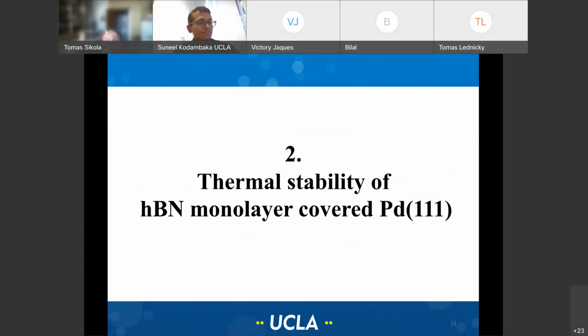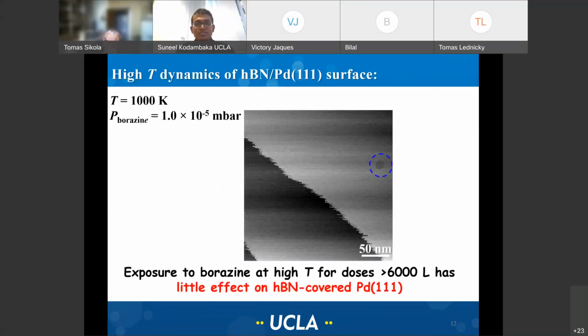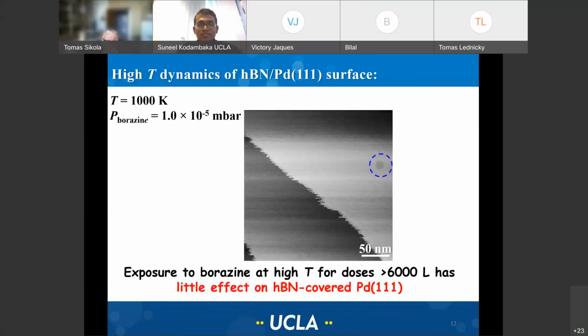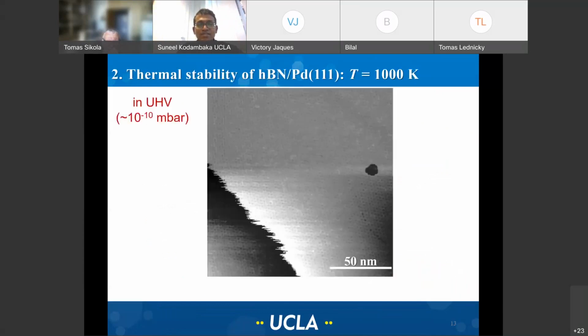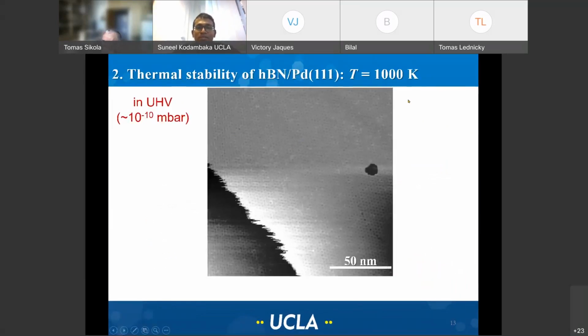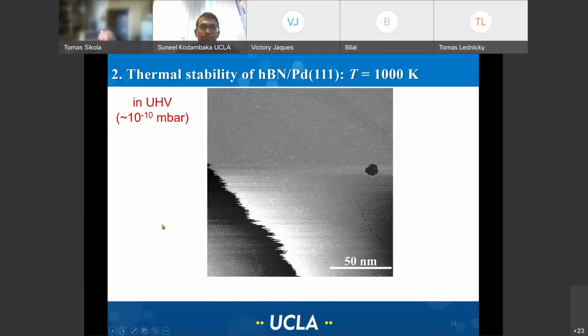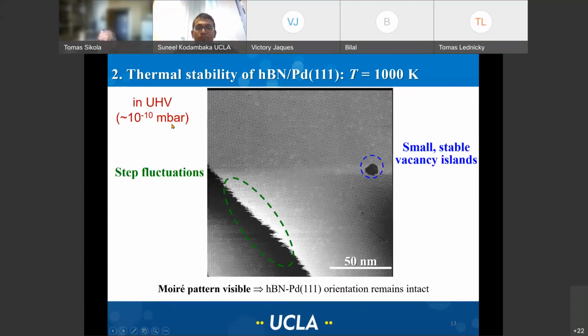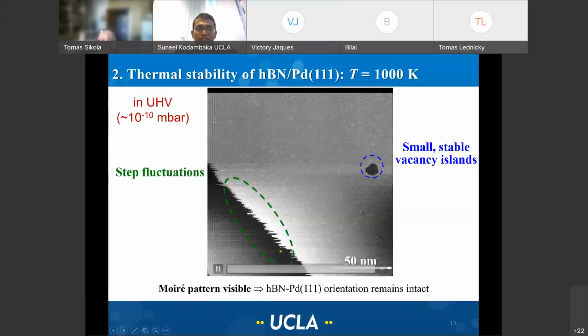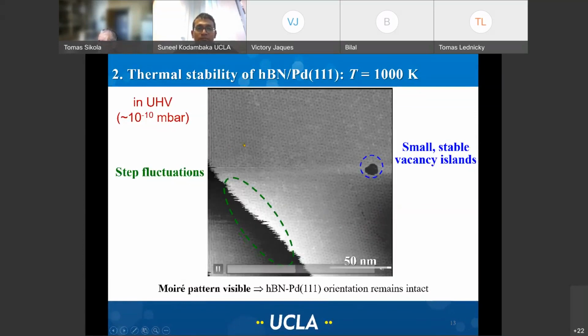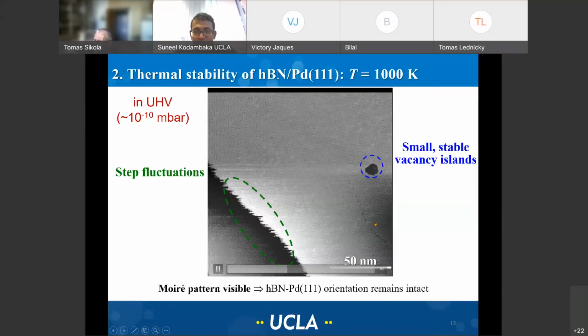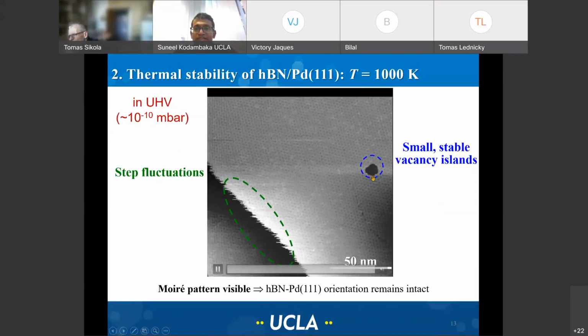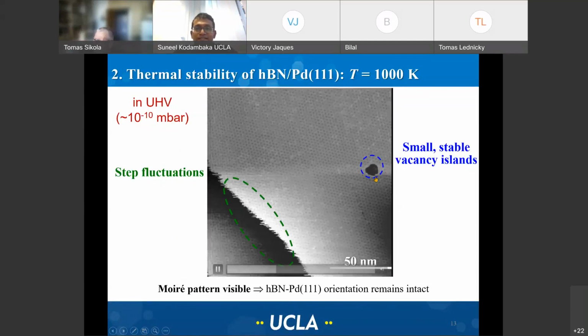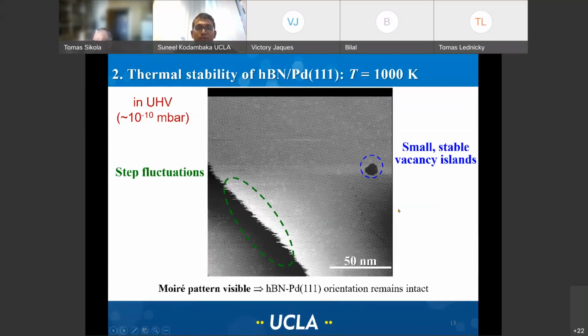And lastly, I have a few minutes left, so let me just show you what is nice about high temperature STM. What you're looking at is a monolayer boron nitride covered palladium surface, and this is being annealed in vacuum. So you're observing the step fluctuations in monolayer hexagonal boron nitride covered palladium, and this is a domain boundary. So you see this defect here, and this is a vacancy island inside this. So there is a carpet of hexagonal boron nitride.